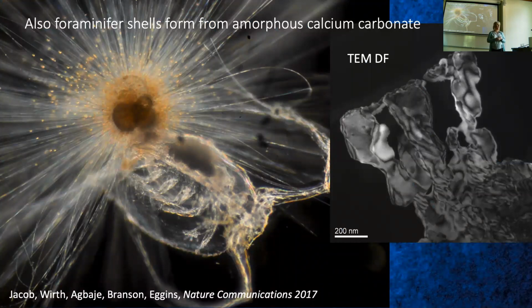And then I had a discovery grant with Steve Eggins together, where we started looking at foraminifera, and we basically found the same thing. Oscar Branson was involved as well, and that's actually one of Oscar's images that you probably all know quite well. And we found the very same thing for most of the foraminifera that we looked at, that they actually start out with amorphous calcium carbonate and then go through metastable intermediate phases until they finally turn into calcite. How fast that happens, we don't know yet. We know everything in the fossil space is calcite, but everything in the alive space is actually ACC first, and you still find patches when you look at the foraminifera shells with the right soft beam protocols.